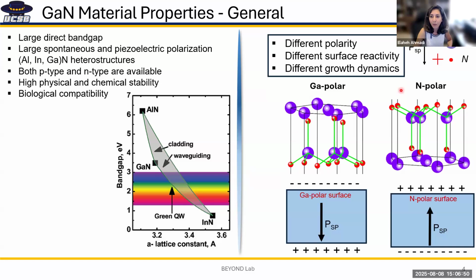If we look at gallium nitride, the unique property that it has is this large spontaneous and piezoelectric polarization. That's because when you look at the gallium nitride bond, there is this spontaneous polarization in the bond, and in the unit cell, because these don't cancel out, there is a net polarization in the unit cell.